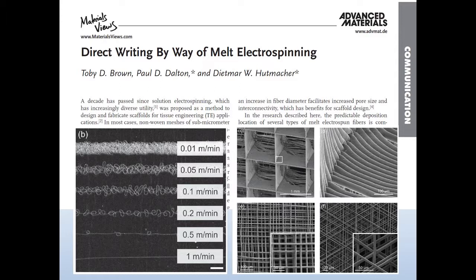And this is really the first time, I think, a paper was published showing that melt electrospinning could be used for direct writing very small fibers. And so the areas of additive manufacturing and electrospinning were coming together. Also, and this is important, not the fact that we can draw a straight fiber, because people have done that before in electrospinning, but actually to stack them up with some volume and height.